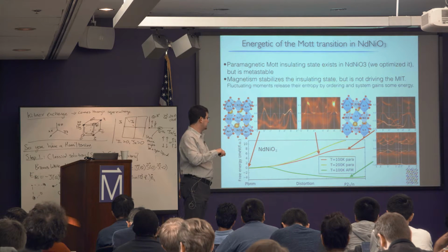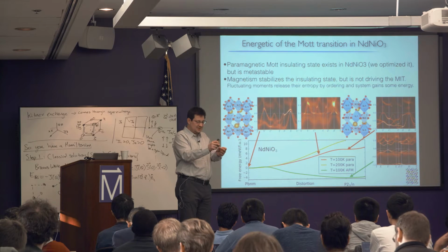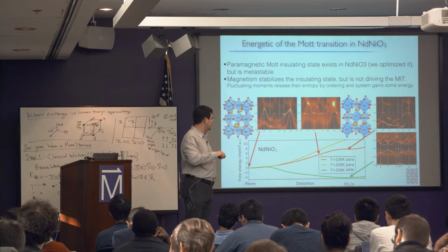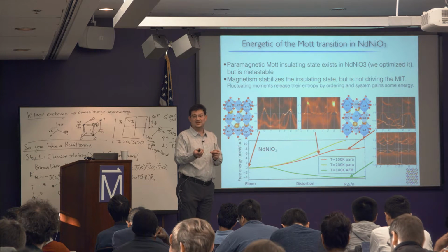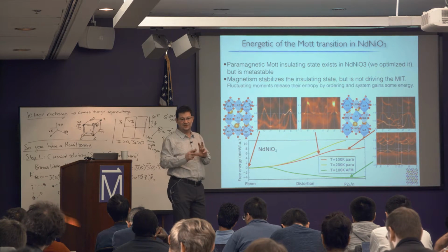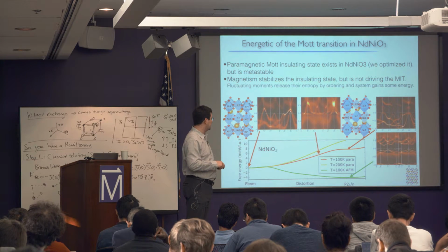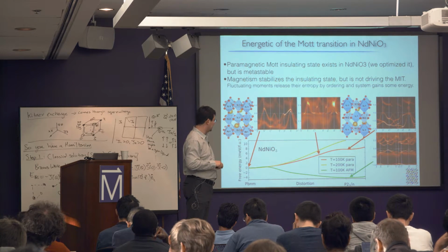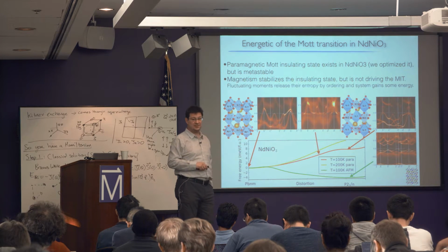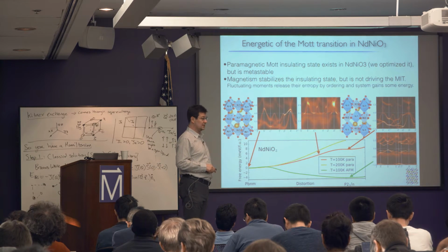Now, without the forces, it's very hard to calculate this metastable phase because it's just a little minimum at this temperature. Of course, this minimum will grow with reducing temperature, but still, if you don't predict the structure very well in this minimum, you're going to be blind to it. There are too many degrees of freedom to tune, lots of internal Wyckoff positions. So here you can get this local minimum, and then you can allow for long-range order, and you see that magnetism reduces the total energy quite substantially. So you can get the second minimum to be more stable.